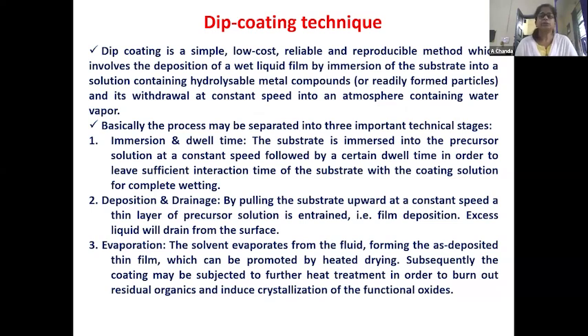So this dip coating process can be separated into 3 different stages. That is, as I told, immersion and dwell time. Dwell time means the interaction time of the substrate with the coating solution for complete wetting. And then deposition: by pulling the substrate upward at a constant speed, a thin layer of the precursor solution is entrained. That is, film deposition occurs. Then evaporation: the solvent evaporates from the deposited thin film, which can be promoted by heated drying. Subsequently, the coating may be subjected to further heat treatment.